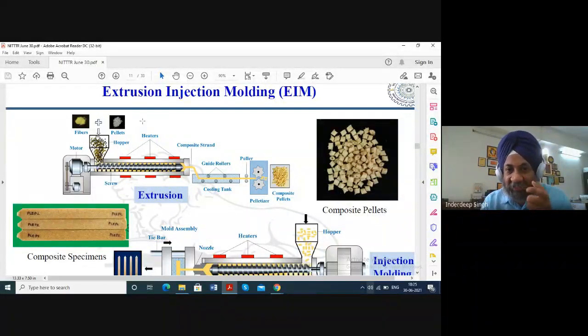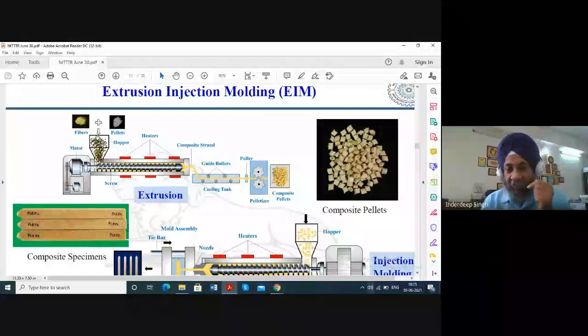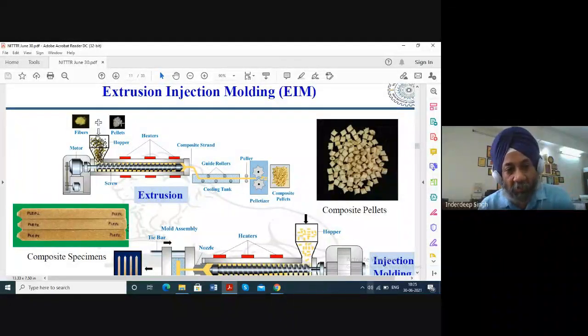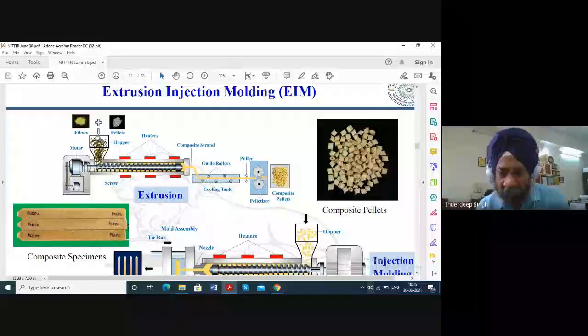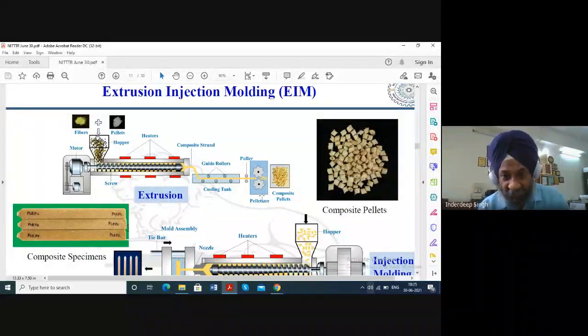In direct injection molding, we were feeding both fibers and pellets directly into the hopper. Here, instead of feeding directly into injection molding, we are feeding them into an extrusion setup. In extrusion, we are extruding using a similar principle, and then we get a composite strand which we then pelletize. Pelletizing means cutting it into standard sizes, and then we get a composite pellet. Composite pellets are clearly seen here. These pellets have fibers and the polymer.